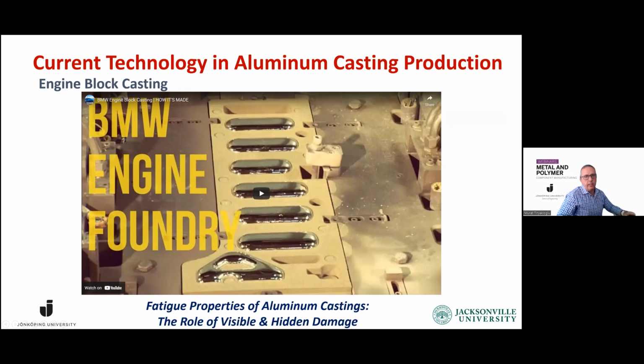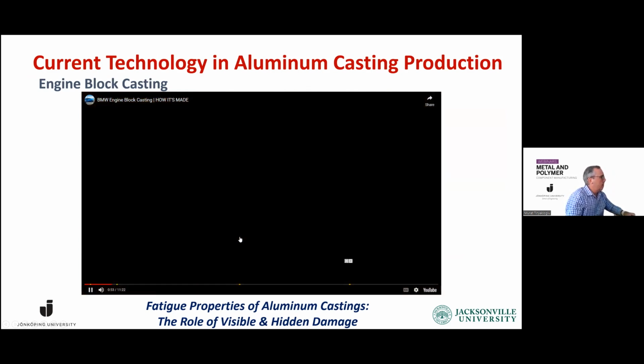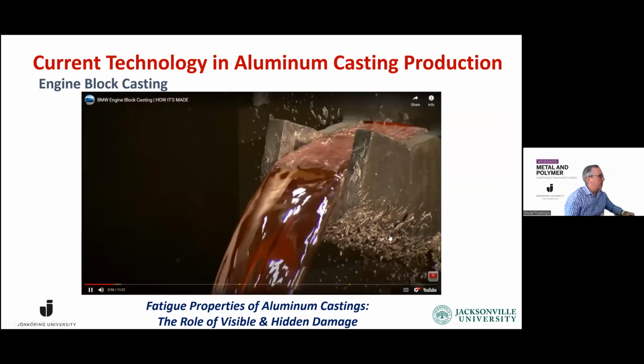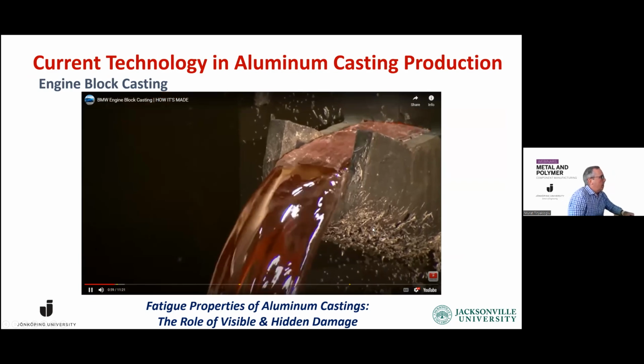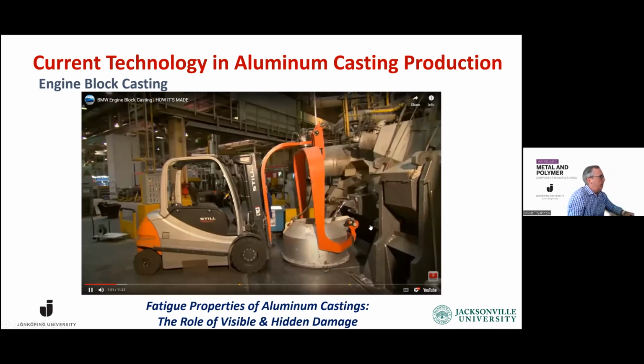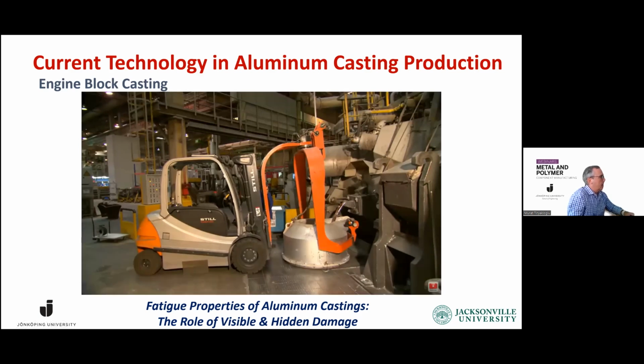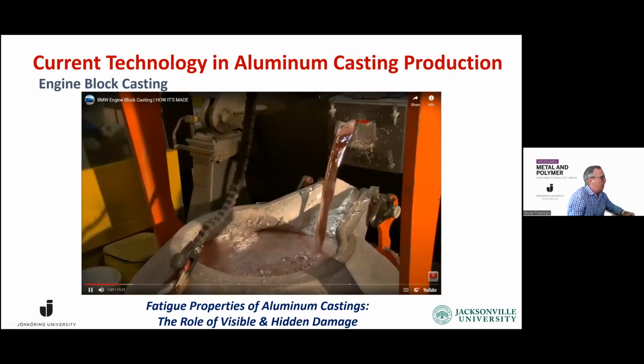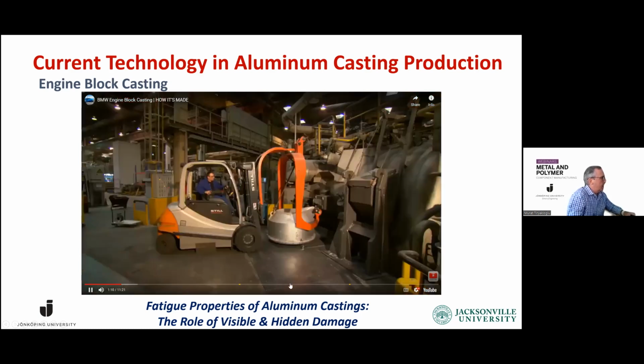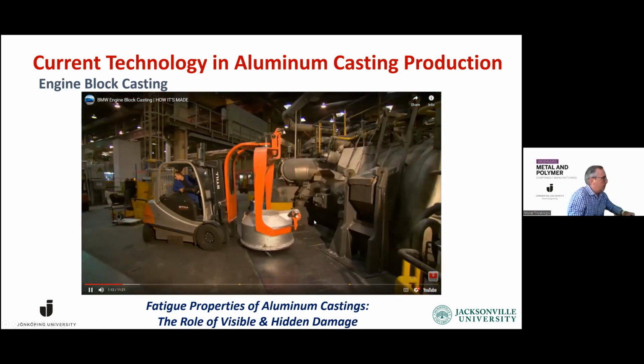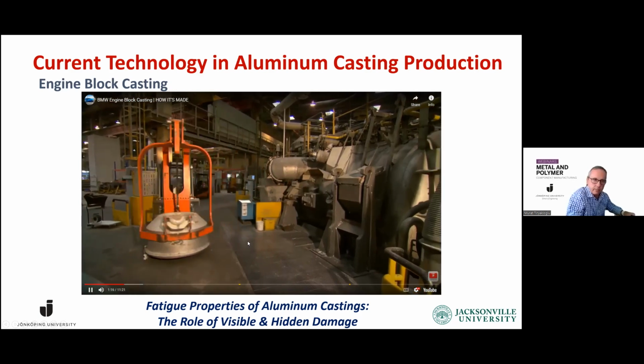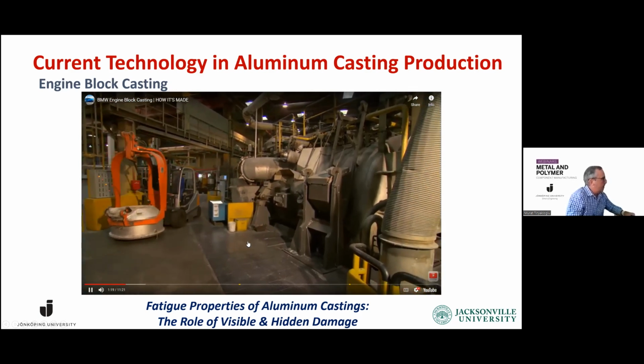When we look at how we treat liquid aluminum in the production of aluminum castings, I found this video online, a YouTube video. So I would like to show a small section of it. We have the central melting furnace, and it's away from where the casting is produced. So the liquid metal has to be transported, and you see how bubbles formed when it was being poured into this ladle. The ladle is taken away by a forklift.